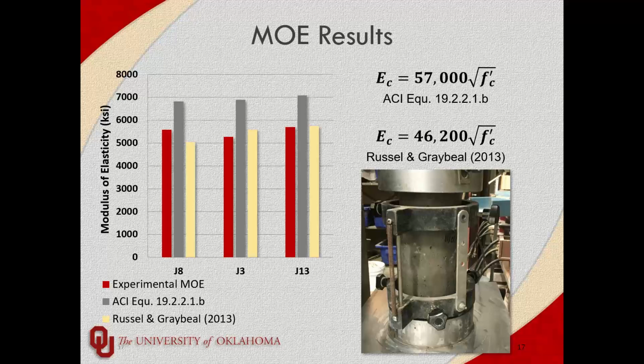So they adjusted that multiplier, and one thing we found was that adjustment worked really well with our mixes. We were at our farthest still less than 10% different than the Russell and Graybeal equation with all of our tests. So I think it's a pretty good equation to use. And I know last I heard, FHWA was creating a specification for UHPC, and I hope they put that number in there because it seemed to work really well with ours. But as expected, the ACI equation over-exaggerated the stiffness based on the compressive strength. Next slide.